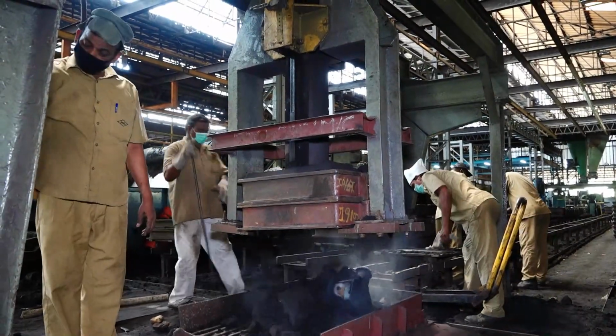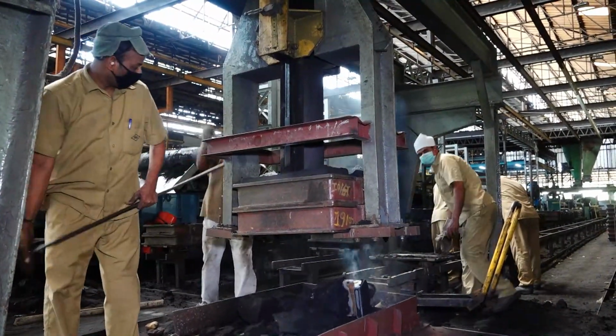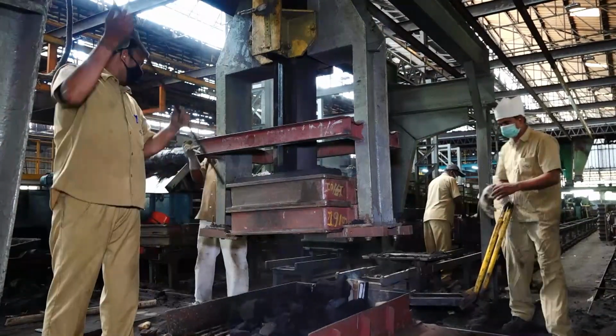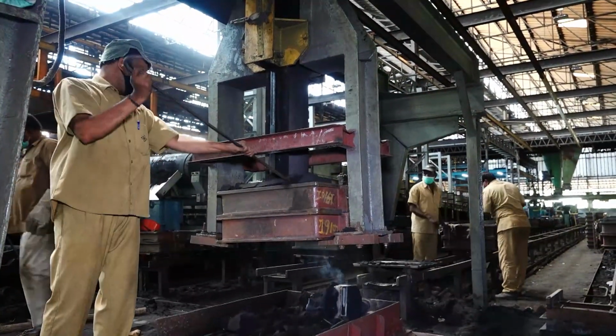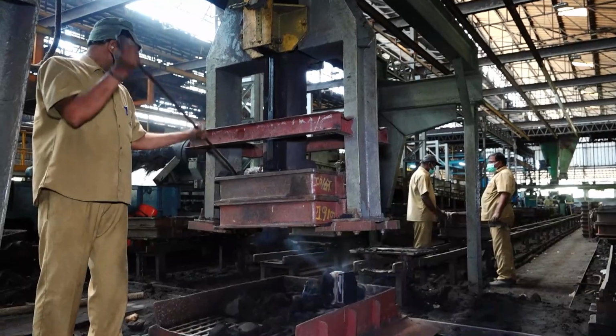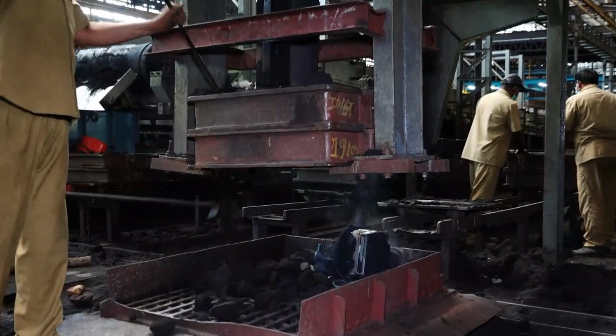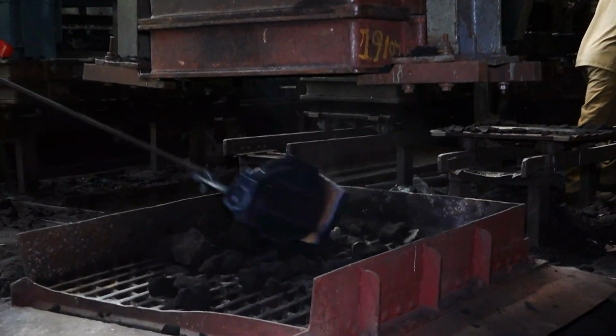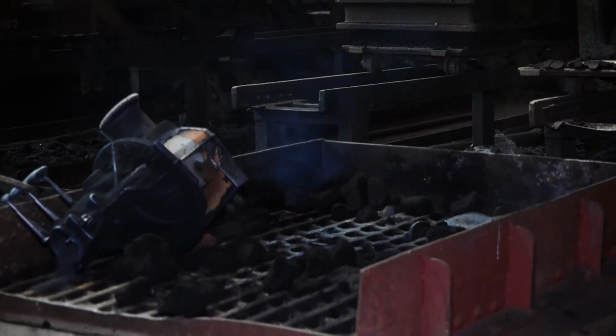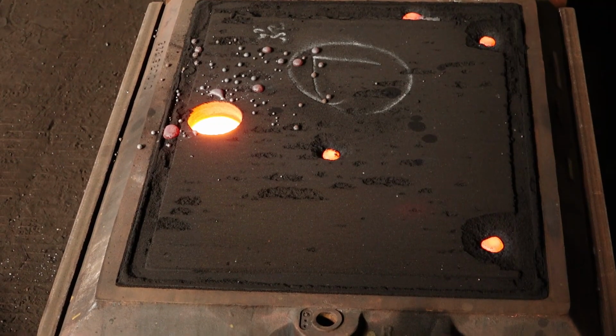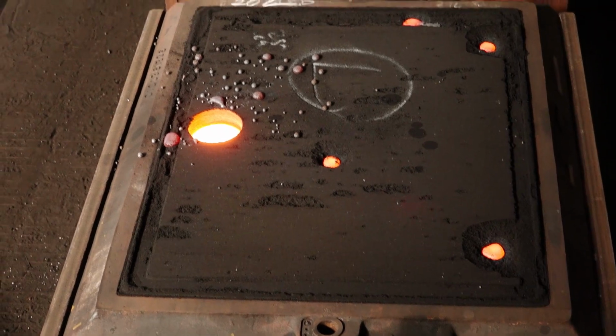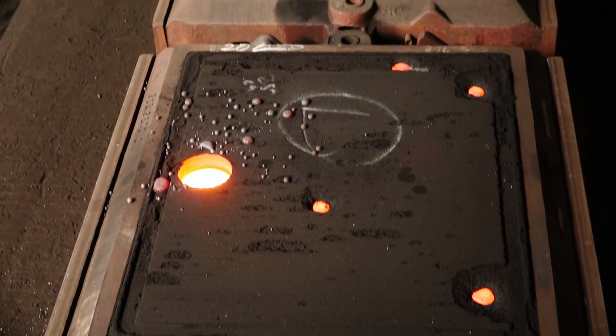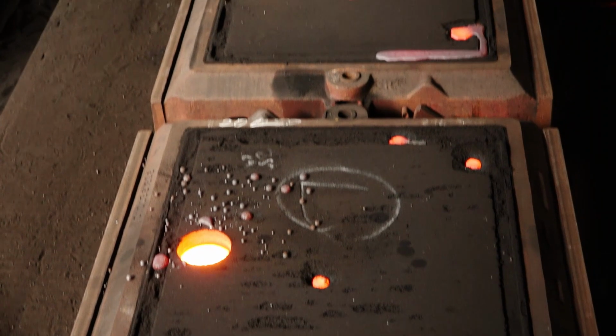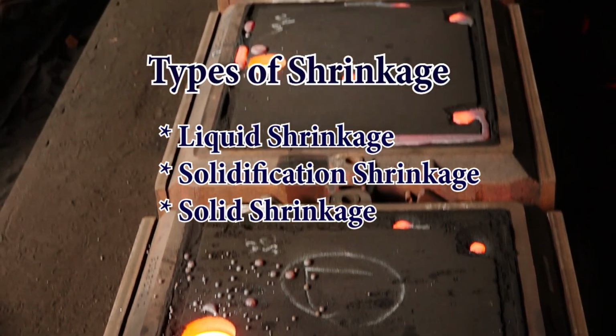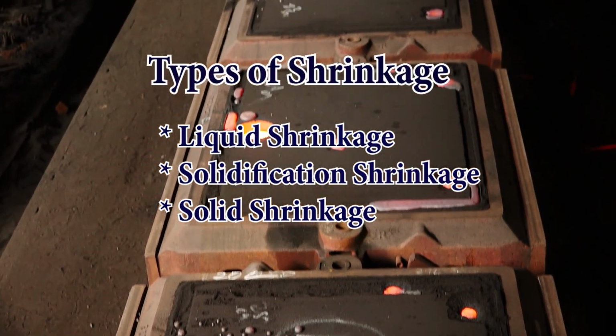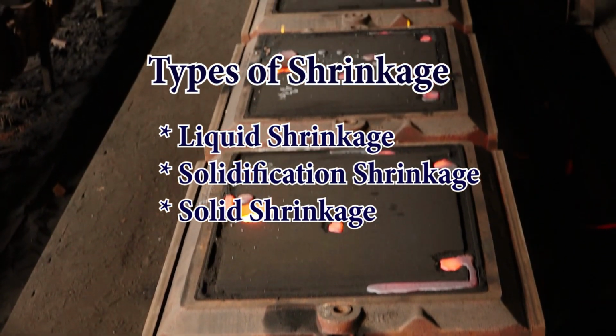Chvorinov's rule states that a casting with a higher volume to surface area ratio cools and solidifies more slowly than one with a lower ratio. So, the riser is designed to have a larger volume to area ratio, so it solidifies last to minimize the effects of shrinkage. When metals solidify and cool to form a casting, they generally undergo three distinct stages of volume contraction or shrinkage. The types of shrinkages are liquid shrinkage, solidification shrinkage, and solid shrinkage.